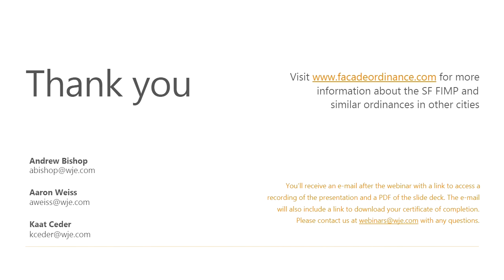Okay, this person said, I've heard that exterior panes of fully tempered glass is good for heat stress resistance. Please advise. Yeah, you're spot on. And this is where it becomes a balancing act. Fully tempered glass is the strongest glass, which makes it less likely to have thermal stress breakage. But then, by having tempered glass, you introduce a new risk of, A, when the glass breaks, it immediately can fall out of the opening. And B, you have the heightened risk of spontaneous breakage due to nickel sulfide.